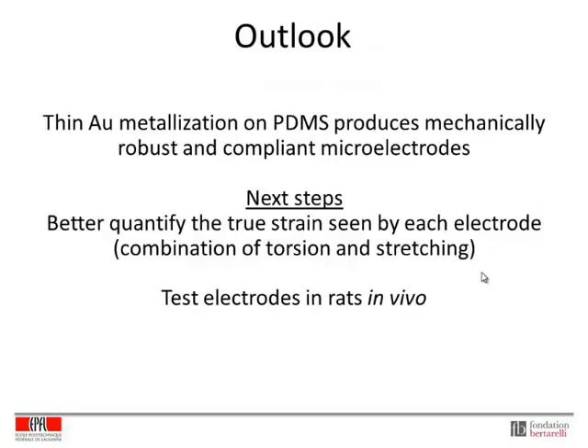In conclusion, we've shown that the gold metallization on PDMS produces mechanically robust and compliant microelectrodes, but we need to improve our current setup by quantifying the true strain seen by each of the individual electrodes on the array due to the combination of torsion and stretching that occurs.